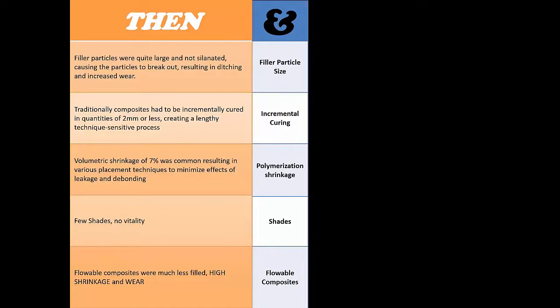Volumetric shrinkage in the industry was accepted at 7%, which is a lot, but that was as good as it was back in the day. We had very few shades available, and I would say the composites of the past did not have the vitality that they do today, and the flowable category was less filled. They were radiolucent in most cases, which created problems if they were ever put in the bottom of a proximal box. They had a very high shrink rate, and they were very prone to wear.